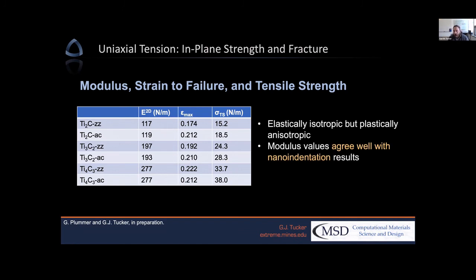And I think a really valuable piece of information that came out of this is that what we see is the MXenes, at least in this case, the bare MXenes, are elastically isotropic, but plastically anisotropic. And that's a very important thing to understand. And that the modulus values that we calculate from these uniaxial tests agree well with the nano-indentation results we did earlier. So we're getting very consistent modulus values. And now we're actually getting a trend in regard to the tensile strength of these materials.